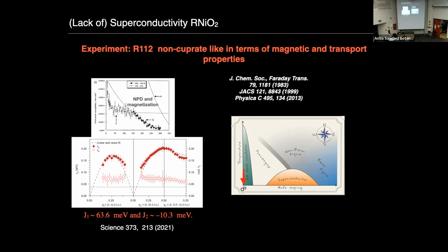Remember that for cuprates at d9 filling, you expect to find an antiferromagnetic insulator. It turned out that in these materials, there is no signature for long-range magnetic order, even though we now have evidence of strong antiferromagnetic correlations. And as I'll show you in a second, the resistivity actually shows metallic behavior. So again, not quite like a cuprate. And I guess that's probably what made people think for quite a few years, well, this is not very promising.